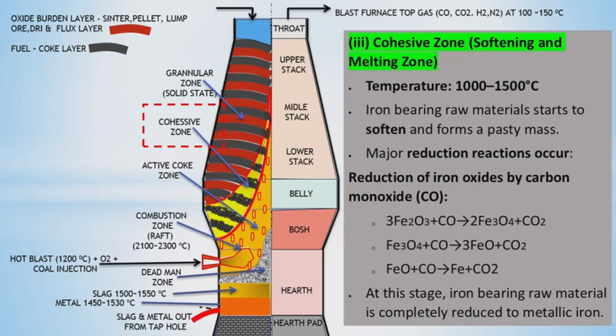Major reduction reactions occur. Reduction of iron oxides by carbon monoxide. 3Fe2O3 + CO = 2Fe3O4 + CO2. Fe3O4 + CO = 3FeO + CO2. FeO + CO = Fe + CO2. At this stage, iron-bearing raw material is completely reduced to metallic iron.